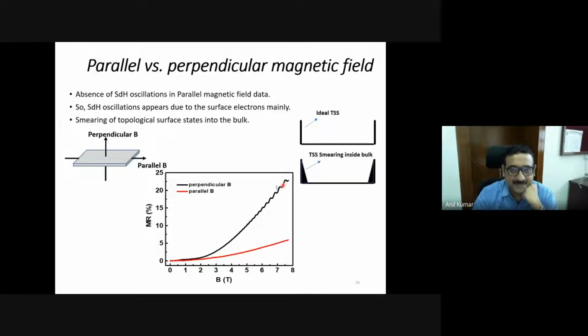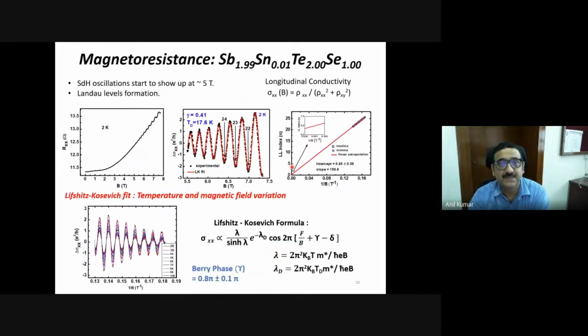People have done this. If I apply magnetic field perpendicular to the sample, then I see an oscillation. But when I apply it parallel to the sample plane, then I don't get this oscillation. But these oscillations can give you a lot of information about the topological surface state in this material. So from this, you can subtract the proper background, and then you see that there are oscillations here.